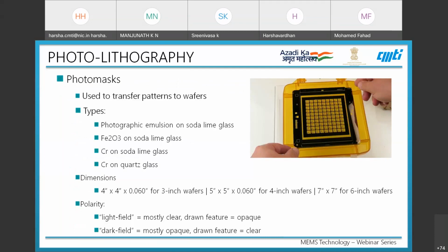The different types of photo masks available are photographic emulsion on soda lime glass, Fe2O3 on soda lime glass, chromium coated with a thickness of about 50 nanometers on soda lime glass, or chromium on quartz glass for very high resolution requirements.